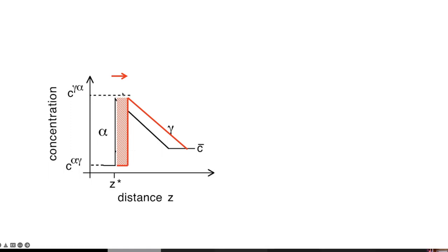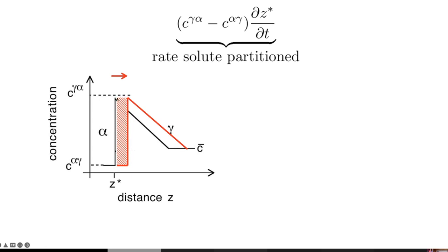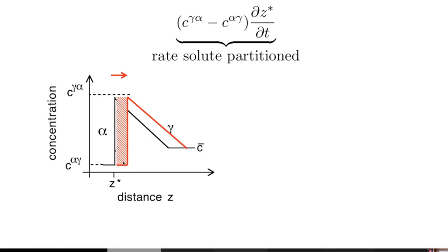And the rate at which we are accumulating this carbon in the austenite is simply given by this concentration minus this concentration, multiplied by the increment in the length of the Widmanstätten ferrite and divided by the time interval in which that increment happens. In other words, this is the lengthening rate of the Widmanstätten ferrite, and this is the amount of solute that must be partitioned into the austenite as the interface advances. And if it continues to partition, then we will lose local equilibrium.